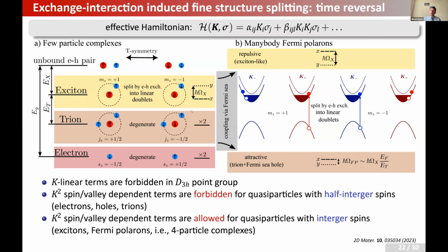So what we can expect, if we deal with trions, is that there are no low wave vector spin or valley dependent terms in the Hamiltonian, just because of the time reversal. In fact, k-linear terms, something like k times sigma, are forbidden by the D3h point symmetry of the system, and the quadratic terms are forbidden by the time reversal symmetry. If we deal with excitons or Fermi polarons, then these quadratic terms are possible.